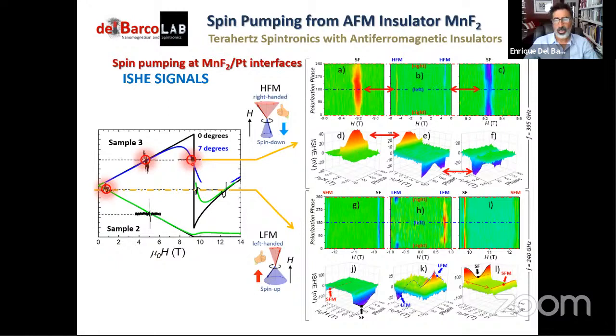But again, I'm gonna show you what happens beyond those points. So we go to the spin flop transition. What we see is very similar behavior of the spin flop transition peak when compared to the high frequency mode. So basically strong absorption when right circular polarization is directed here and here, very weak, also not zero. There's some background signal in the spin flop transition that is not in the high frequency mode. And when we reverse the field, it's the same thing, right? So somehow, and you look at the three-dimensional picture, it's basically behaving the same way, right? So close into the spin flop transition, the system, you know, remembers the high frequency mode nature.